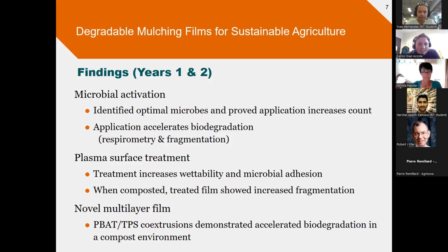We did the plasma surface treatment. So we demonstrated that it increases the wettability and the microbial adhesion, and that the treatment or the surface activation stays. There is no recovery back to the original, so we can have a long-term treatment. And when composted, the treated film shows increased fragmentation. Now for the novel multi-layer film, PBAT, that's the most commonly used polyester for biodegradable films, and TPS, thermoplastic starch, we co-extruded it, and we demonstrated that this concept accelerates the biodegradation in a compost environment.